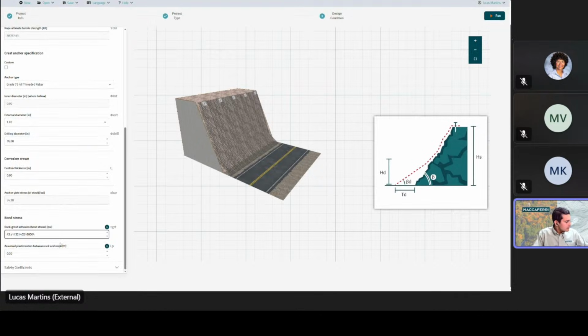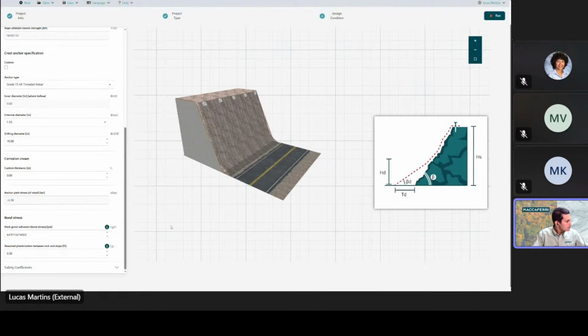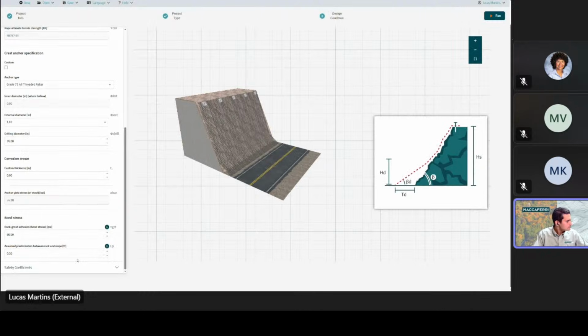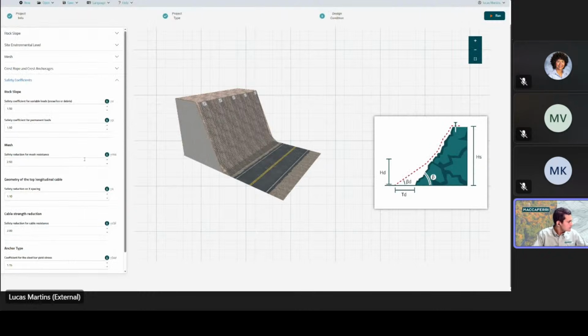Now the bond strength. The bond strength is a value that can come from a site test or from the literature. If you click on the little I, it gives you a little cheat sheet here for some bond strength, grout adhesions, bond strength for certain types of rock. Let's enter the granite and basalt one. Plasticization. This is also something that has to do with the site. It is the shear band size. Here are some plasticization values that you could use. But let's leave it at about 10 centimeters.